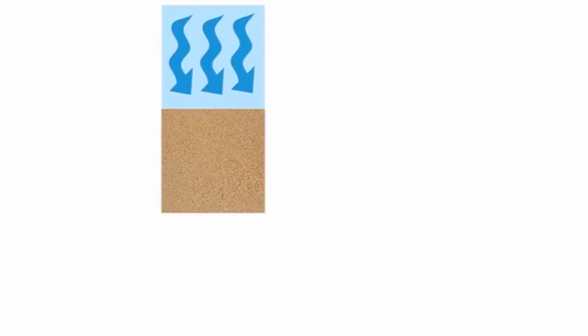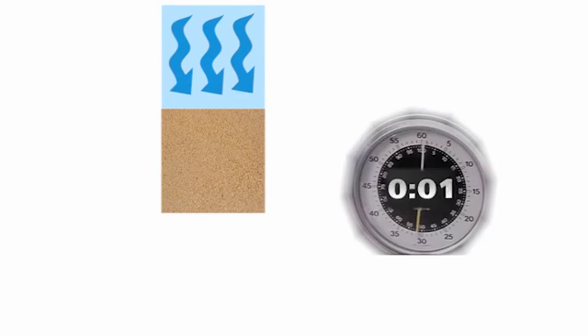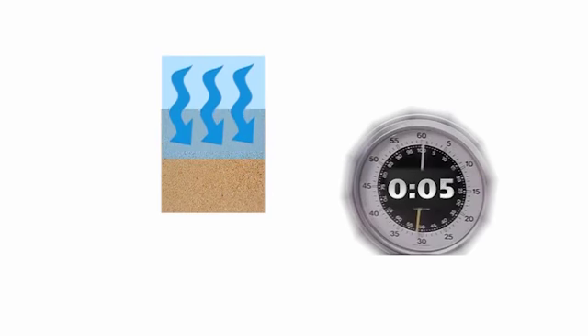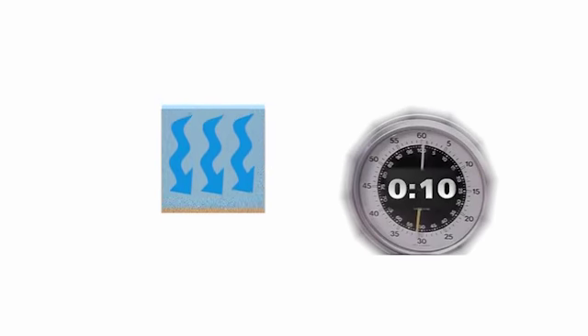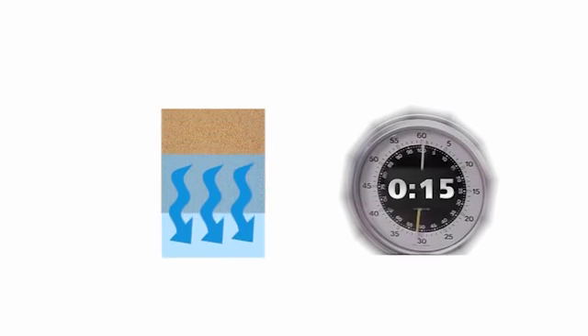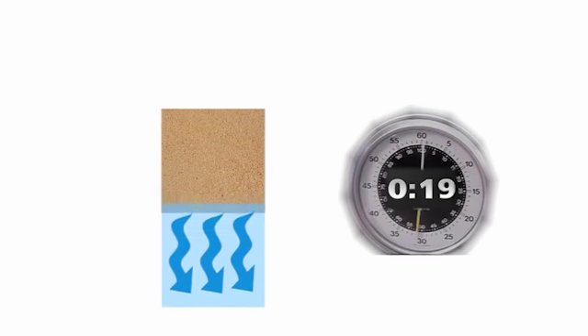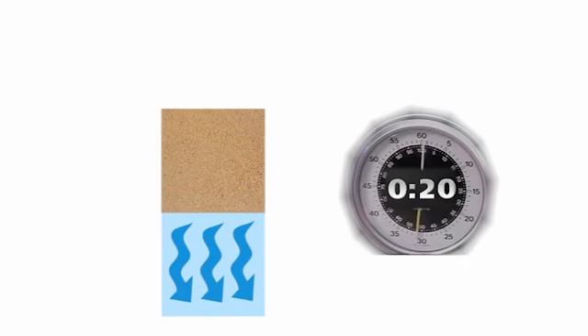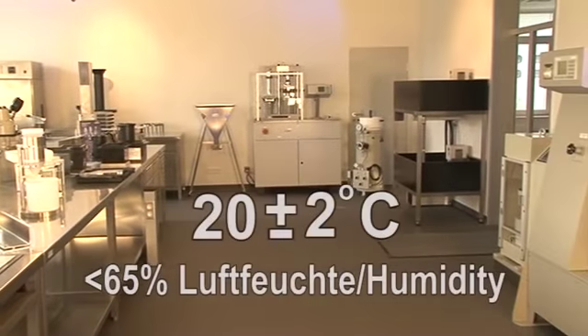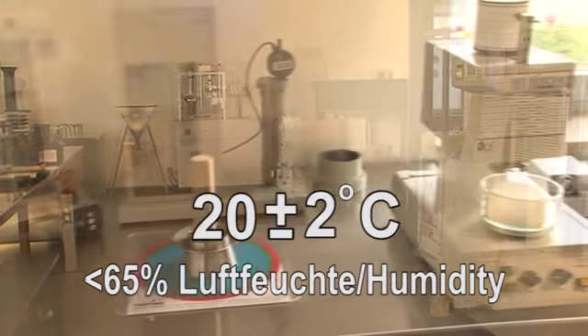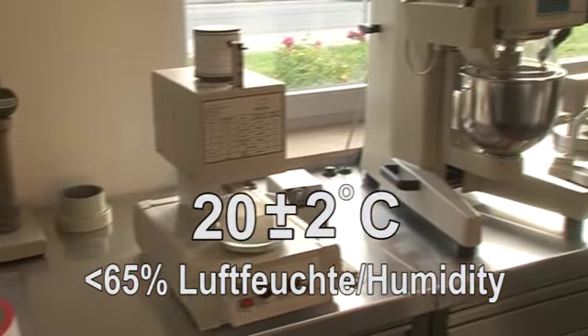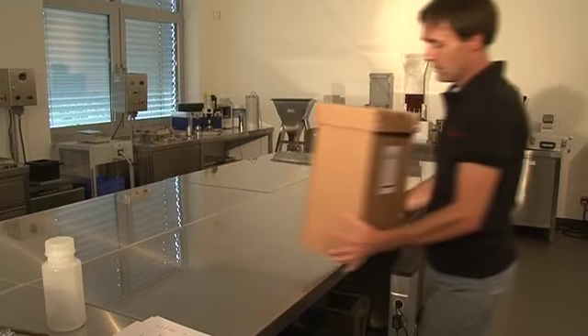To determine the grinding fineness of cement, its specific surface area must be established from the air permeability of an accurately defined compacted cement bed. This is done by observing the time taken for a fixed quantity of air to flow through the cement bed. This time is then a measure for the specific surface area, which is indicated in square centimetres per gram. The laboratory, testing equipment and test material must have a temperature of between 18 and 22 degrees Celsius, as well as a maximum relative humidity of 65%.